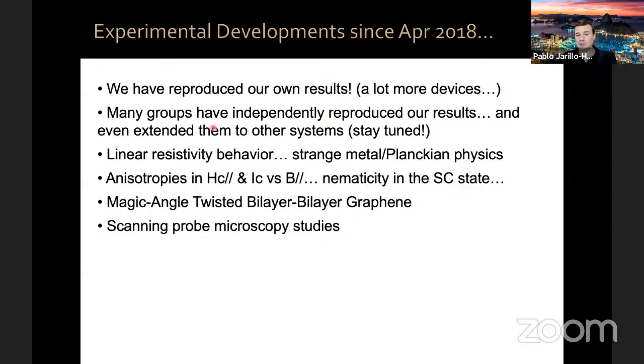This type of correlated physics, in particular correlated insulator behavior, has been extended to many other systems, such as magic angle twisted double bilayer graphene. Now you have bilayer graphene, the usual bilayer graphene, you get another bilayer graphene, and you stack them on top of each other, so four layers this time, pairwise like this at a magic angle, and you also see correlated physics and interesting magnetic properties of the correlated insulator states. There have been many groups now doing scanning probe microscopy studies: scanning tunneling microscopy, scanning nanoSQUID, scanning near-field optical microscopy, scanning single electron transistor. All of these are looking at the microscopics of the system, looking at something, for example, such as the twist angle disorder, looking at how interactions look like locally, how these anisotropies look locally in space. So these are all very interesting studies.